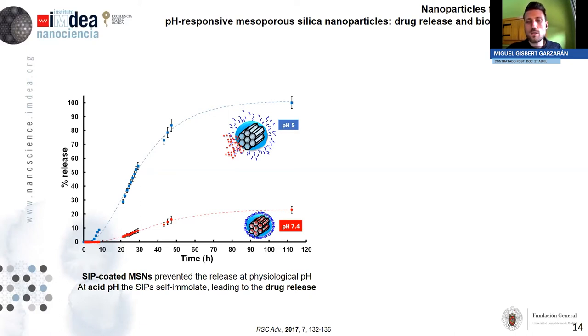remains unaffected. So it closes the mesopores of the nanoparticles, so the payload remains inside. However, at pH 5, it self-immolates. So there is nothing on the surface that prevents the drug from going out. So in the end, we have this drug release. So we can conclude that this self-immolative technology can indeed be used as gatekeeper for mesoporous nanoparticles.